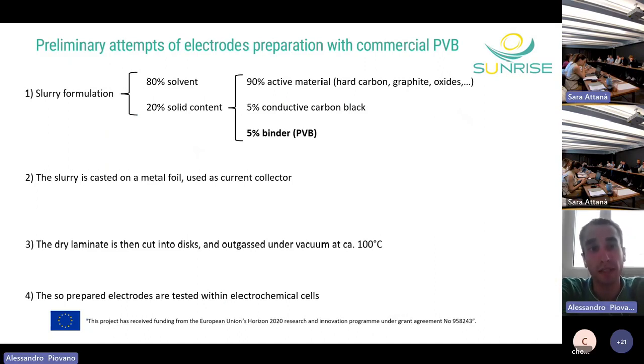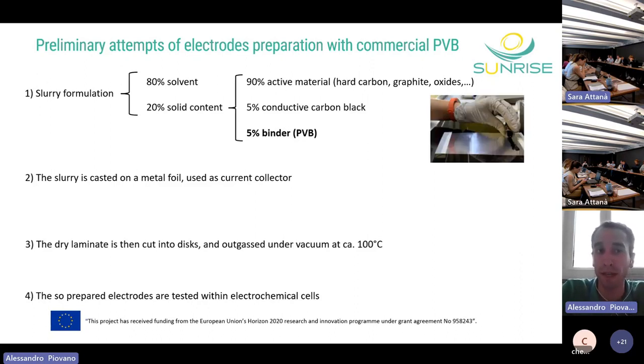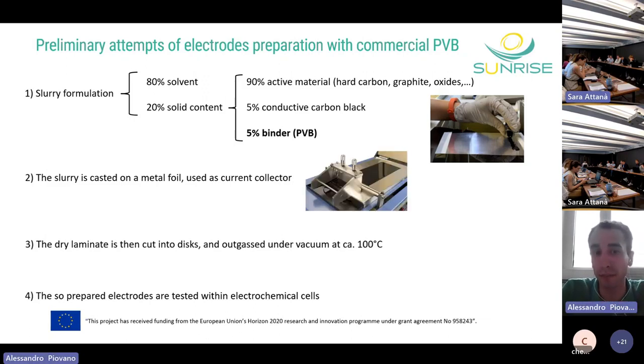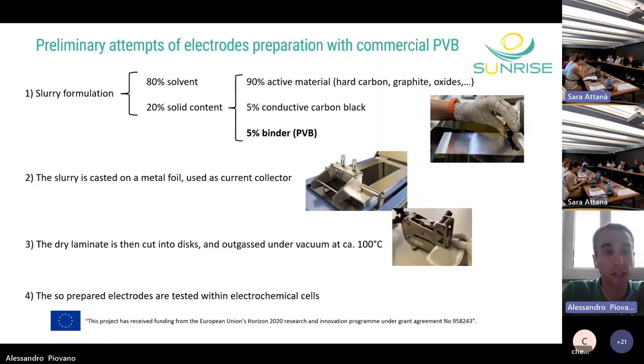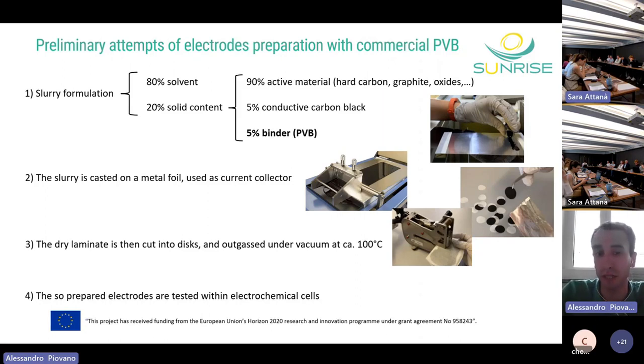We have already done some preliminary attempts of preparing electrodes with PVB as a binder. We started with pure commercial PVB for this preliminary test. For the preparation of the electrodes, first we have to prepare a slurry that contains a solvent and the solid content, that is the material of the electrode. In particular, the solid content is composed of the active material, which can vary depending on the anode or the cathode, the conductive carbon black, and the binder. Then the slurry is cast on a metal foil that is used as current collector. The dry laminate is then cut into discs and outgassed under vacuum at 100 degrees. And finally, the electrodes so prepared are tested within electrochemical cells.